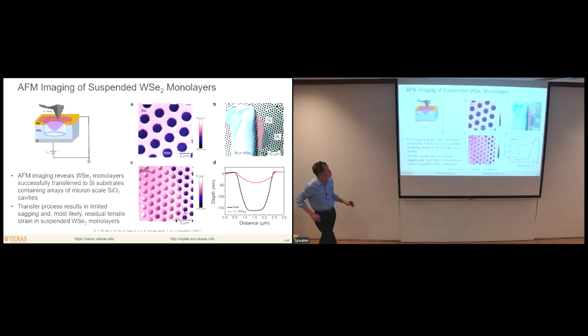All right. So what I've shown here is just an image of an array of these cavities that we've created. You can see they're about 150 to 200 nanometers, in this case a little over 150. This is an optical microscope image of a tungsten diselenide layer transferred onto this array, and the region corresponding to monolayer material is highlighted here in pink.